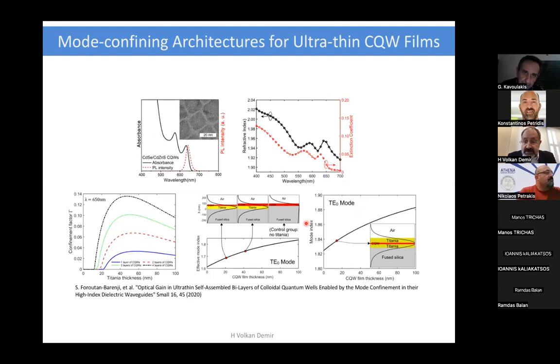With this understanding, we wanted to see whether we could push down the number of monolayers at which we observe gain. In this case, we used additional assisting films, for example, on fused silica, titania with higher refractive index, allowing us to better confine the optical mode in the vicinity of the colloidal quantum wells. We were able to see, yes, we can do better. For example, we can have 2 monolayers to observe gain instead of 6 monolayers using such a structure. And one can quickly think about using a single titania layer, which would be good enough to help increase confinement, or one can do an even more symmetric structure. But remember, still we have air on the top and fused silica on the bottom. So not purely symmetric, but closer.